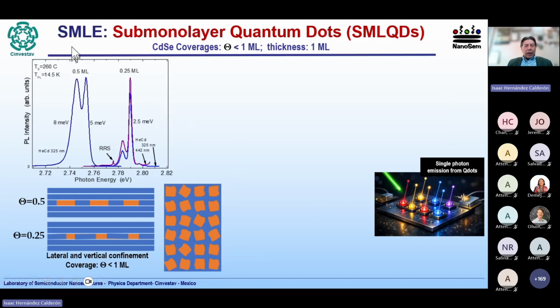Additionally, using this technique, the submonolayer epitaxy technique, we can grow submonolayer quantum dots. What we want to say with submonolayer is that the coverage, the amount of material that we deposit, is less than one monolayer. However, this is not contradictory, the thickness of the regions is one monolayer. So this is an example of these monolayer quantum dots with a coverage of half a monolayer, of a quarter of a monolayer, and this is the excitonic emission. They emit in the blue range. That's very interesting. And as a curiosity, they are always with a peculiar two-peak structure.